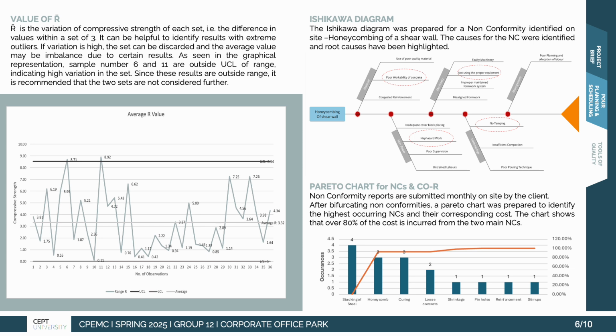An Ishikawa diagram was prepared for a non-conformity identified on site, which is honeycombing of a shear wall. The causes for the non-conformity were identified, and the root causes for the problem were poor workability of concrete, haphazard work, lack of tamping, and not using proper equipment, that is not enough vibration, not enough use of the needle vibrator.